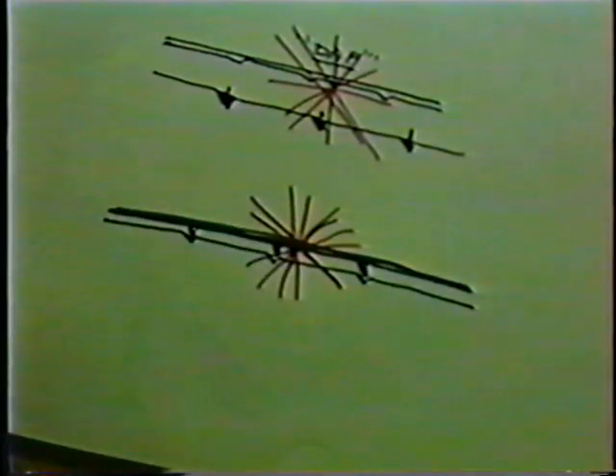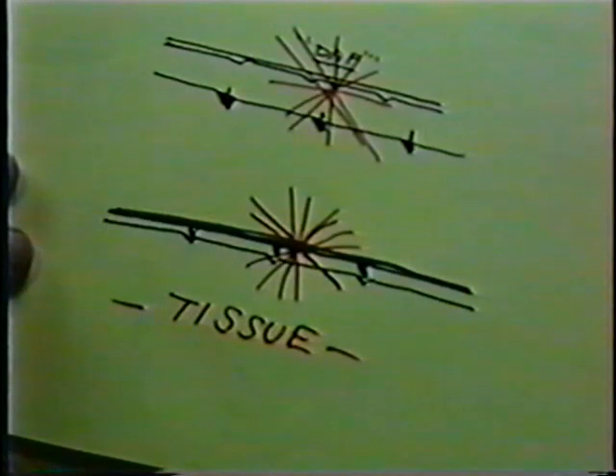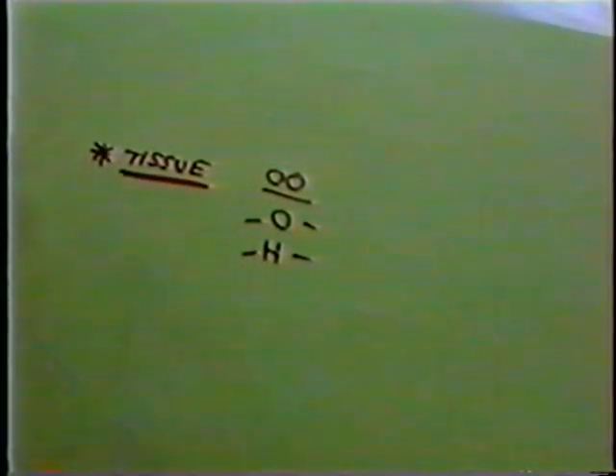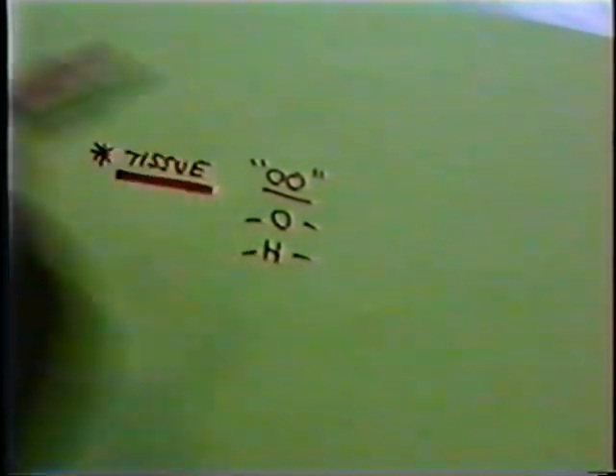But it seems like the only sure way to keep the grain from coming back is this word right here, tissue. If you somehow avoid the tissue, inevitably the grain seems to come back. So what I'm suggesting right now is we go right into the full finish method. We have the three coats on. Cover everything with tissue. I like 00 silkspan. You can use 0, and you can use heavy. There are three grades of silkspan. This will work out the lightest, the easiest to use. I would not consider making a plane that didn't have every outside surface covered with tissue.